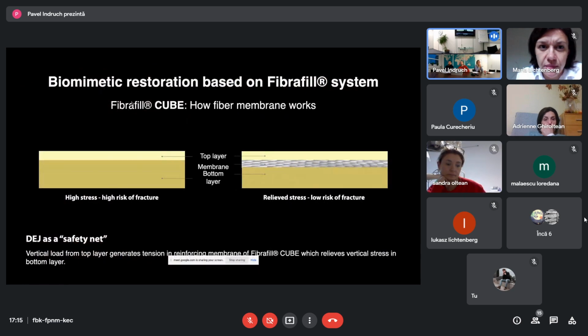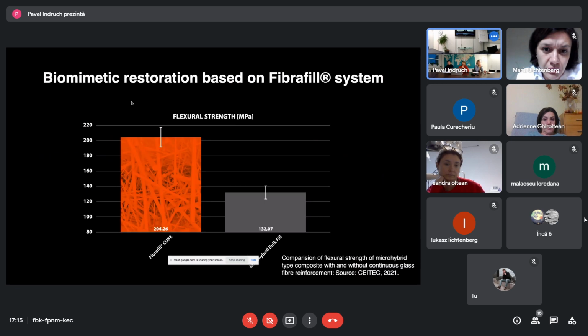Here you can see the principle of how the membrane works in the cavity. When the vertical load is applied on the surface of the material, it generates a tension in the reinforcing layer, in the fibers, and this contributes to relief of stress in the bottom layer. This was also quantified experimentally by a 3-point bending test, comparing the flexural strength of conventional microhybrid composite with and without continuous fiber reinforcement. Flexural strength itself can be interpreted as the ability of the material to resist deformation under masticatory load. And here you can see that the continuous reinforcement works effectively in increasing the flexural strength of the material.